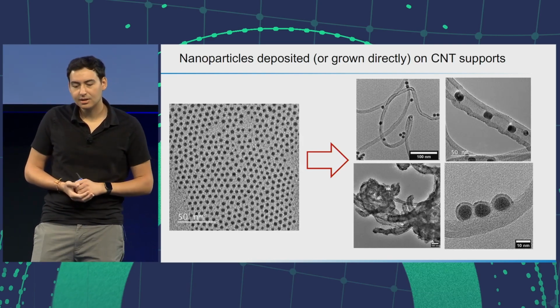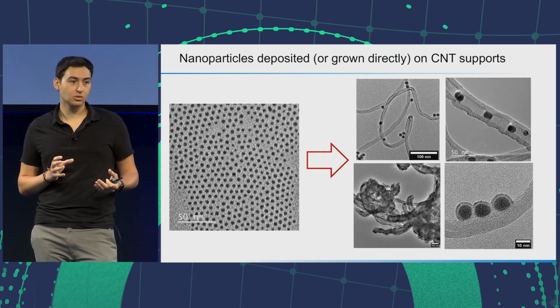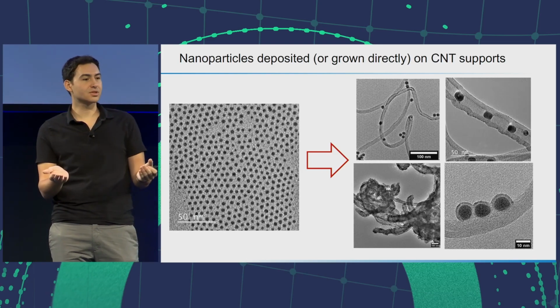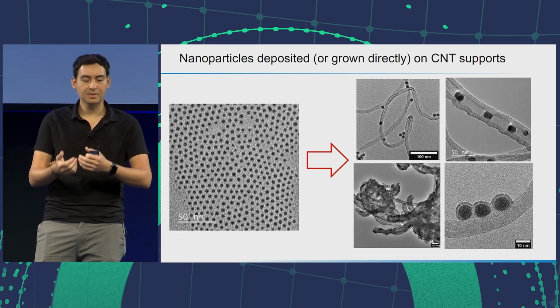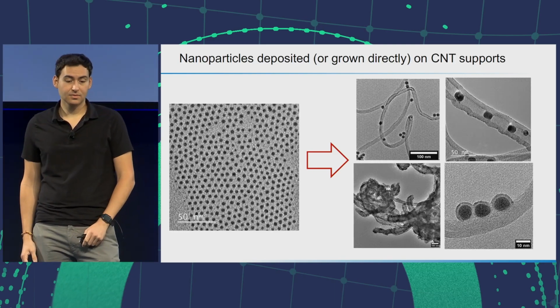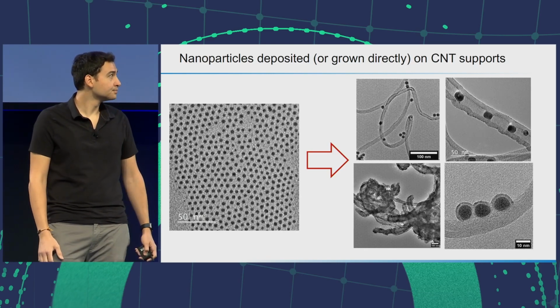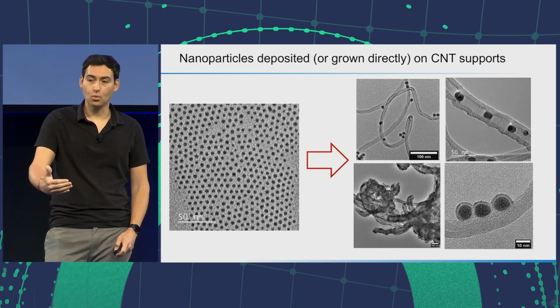But even in the bottom right, you could see we could play with different layers. So this is core-shell nanoparticles. We can form a palladium surface with a nickel core, and play around with tuning our materials at the nano level and making sure that we characterize them so we know what's going in each time.